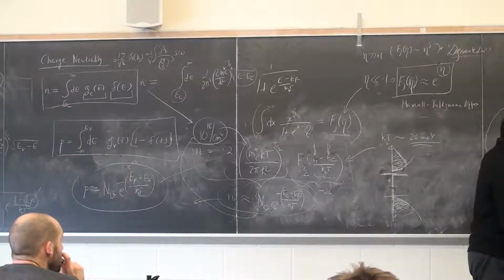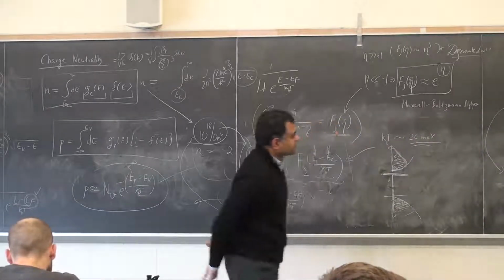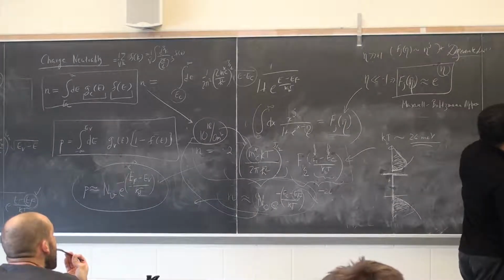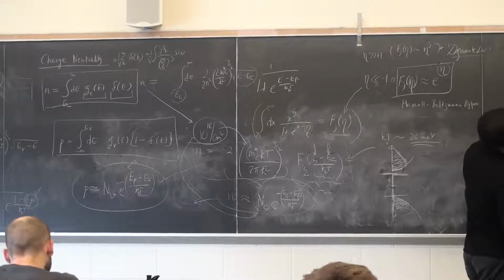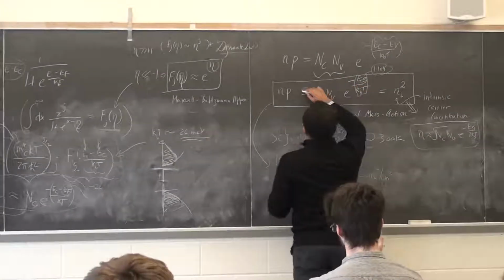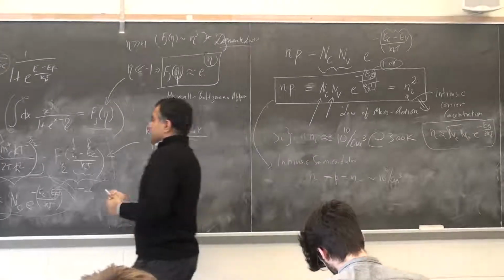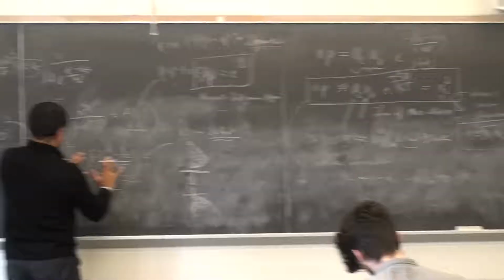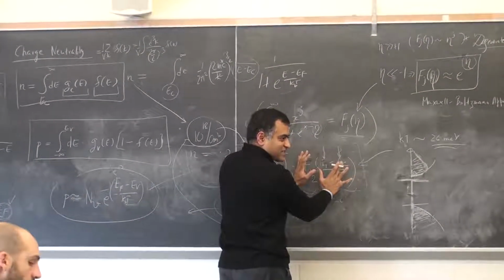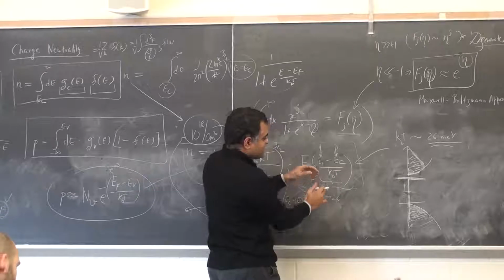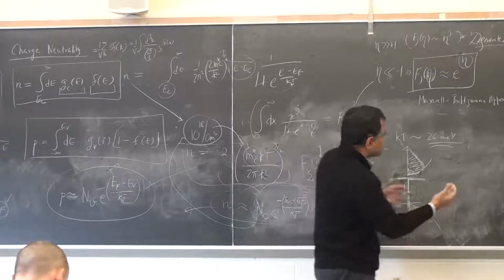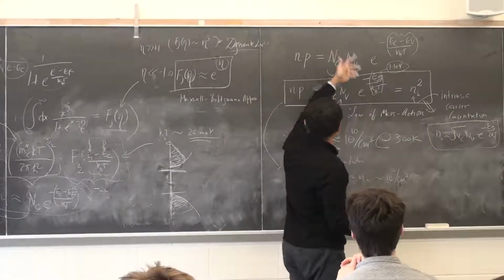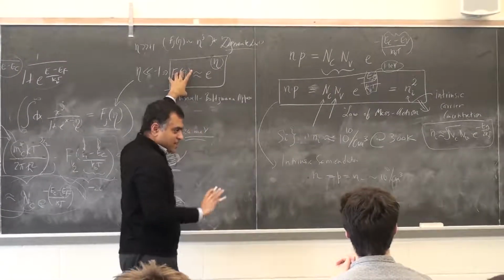Sorry. Yeah, sure. And is this equation just assuming a large EG, and you use them both in the same? Good point. The exact expression will be NC times NV times 2 Fermi-Dirac integrals. That's the exact expression. So if the gap is much larger than kT, then indeed I can make that approximation, and that's correct. Absolutely.